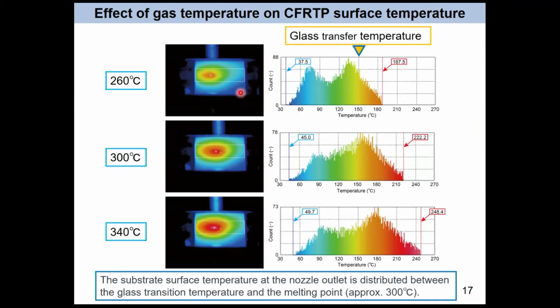This slide shows the temperature distribution in this white box, around the nozzle outlet. When we set the gas temperature to 260, the maximum temperature is about 190. The actual material cannot be shown in this presentation, but the glass transition temperature of this substrate is around 150. So this figure shows the surface temperature around the nozzle outlet exceeds the glass transition temperature, and a thermal softening effect occurs on the substrate.